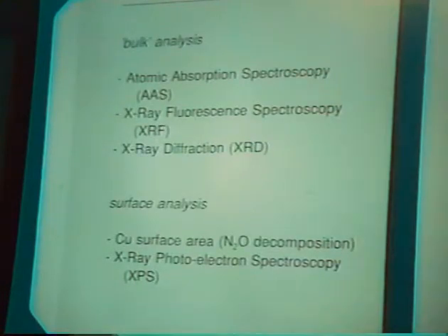We've also done some surface analysis, in inverted commas if you like, copper surface area using the method described by Chin, using N2O decomposition as a method of monitoring the copper area. There is some discussion about how fair it is to say that that's all surface copper, but it is a measure of the copper surface area. And we've done some X-ray photoelectron spectroscopy work to look at the surface concentrations of the additives.